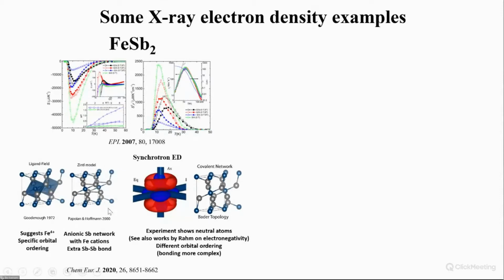Later, Hoffmann looked at it as a Zintl phase, where you have an anionic antimony network and then iron cations donating electrons. This model gave an extra antimony bond, so you have like this ladder structure going up through the structure. You can, of course, ask the crystal itself and measure the data, and then you see that none of this is really correct. There are many details here, but one of the things is that if you look at the atoms, they're virtually neutral. And really, the chemical bonding is like a covalent network, so something in between the 2 other models.